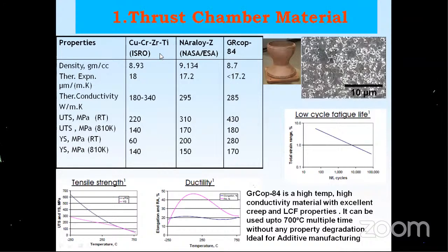You see, now there's a small correction: UTS is actually 170. Sorry. So this is the NASA material developed by NASA, and I worked on all three materials, but I found this is the easiest material, because it can be easily formed and made into any shape, whereas this offers better resistance to deformation and is difficult to forge, because we were not successful, because it needs a special facility called isothermal forging, which we don't have in India.